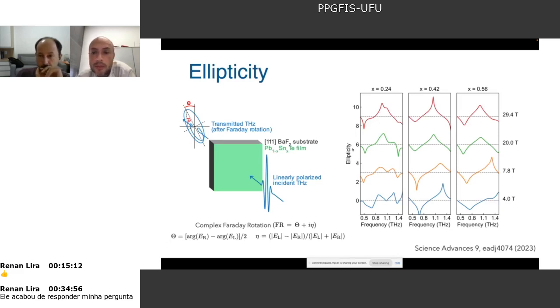So let's look here at ellipticity for different magnetic fields, and we see two peaks, one negative peak and one positive peak. So these two peaks correspond to different chiralities. This phonon has one chirality that gives you the negative ellipticity, meaning it is right-handed, and this one is positive, meaning that this one here is a chiral phonon, left-handed.